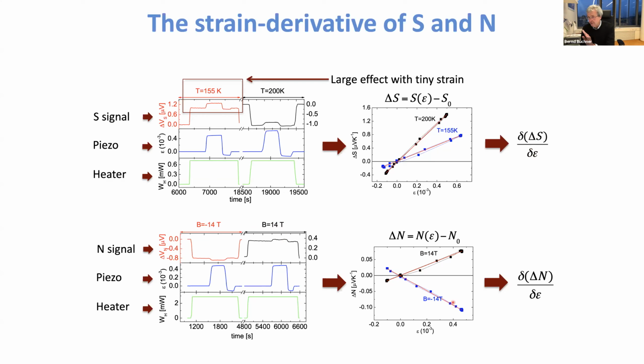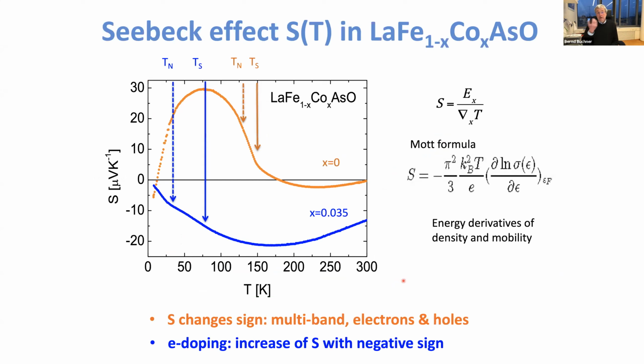That by itself is already a real surprise because typically these effects are zero in usual metals, and now you can even measure their change as a function of these tiny strains. The Seebeck effect, what do we measure here? So it's not scattering. It's really a different quantity than the resistivity. What you measure here, if you, for example, take the easy Mott formulas, is the energy derivative of the conductivity, so energy derivatives of density and mobility. And it's, of course, well known that the Seebeck effect is very, very sensitive to details of the Fermi surface.